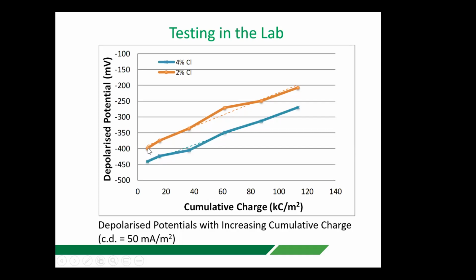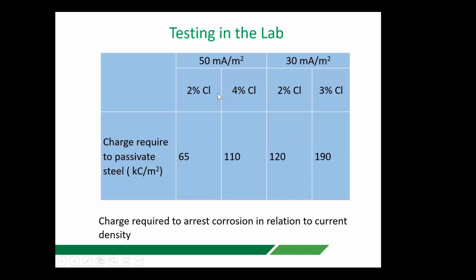We saw that obviously at the beginning the potentials were very, very negative, indicating that the steel was corroding quite a lot. But with time, and it was almost linear, the potential became more and more passive, and moved towards passive regions. And we were able to calculate how much current density we needed, or how much charge delivery we needed to be able to eventually arrest corrosion. And we found that at 50 milliamps per meter squared, for example, at 2% chloride contamination, we were able to do that with just 65 kilocoulombs per meter squared application. Whereas for the same level of pre-corrosion and chloride level, at the lower 30 milliamps per meter squared, we required 120 kilocoulombs per meter squared.